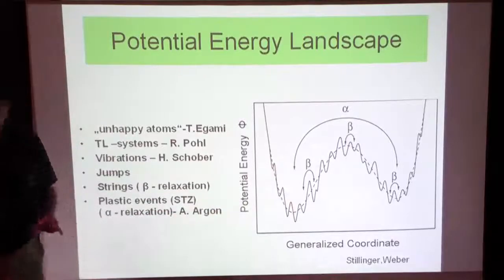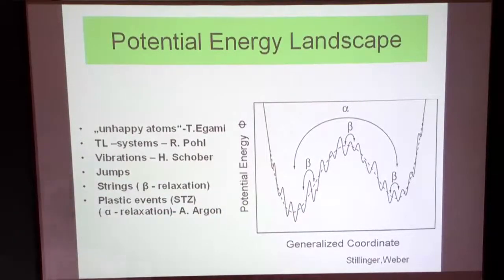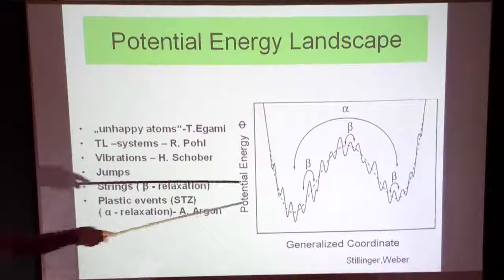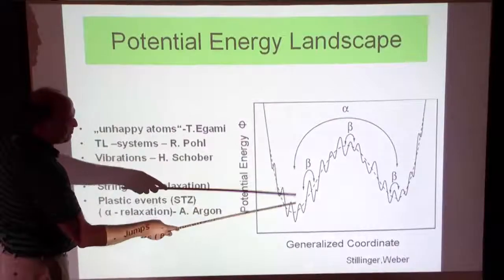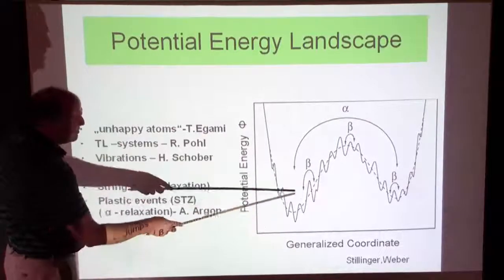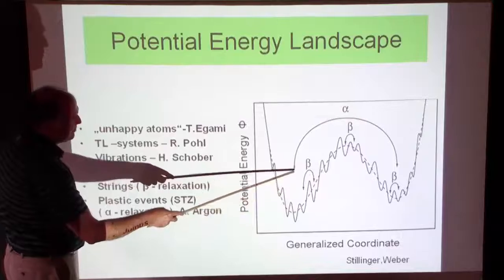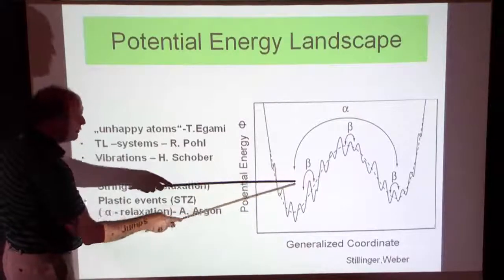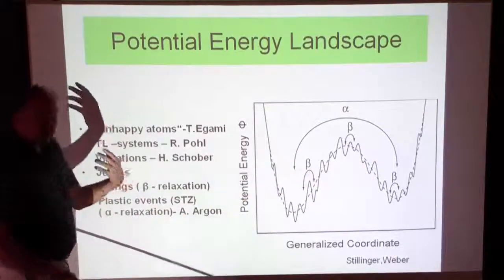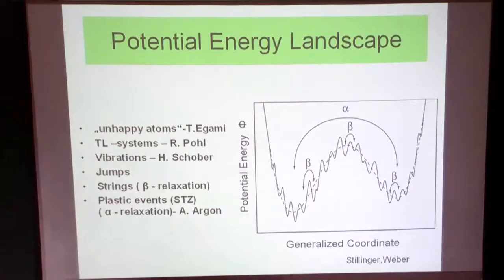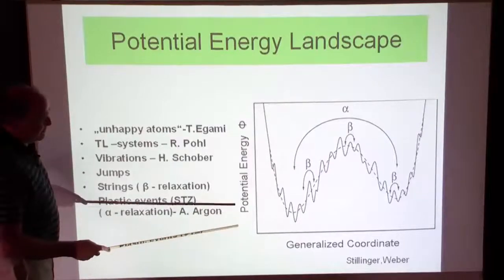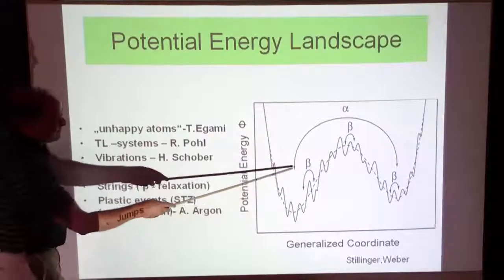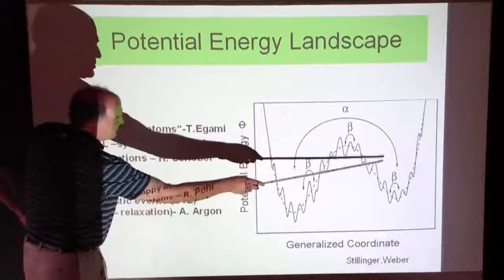You can discuss these aging phenomena in this kind of sense. Diffusion, I will show it to you later on, what that means with the beta relaxation. And then you have, this is reversible. You can get out the mechanical work which you put into the system, to a certain amount at least, by a recovery experiment in the entropy.